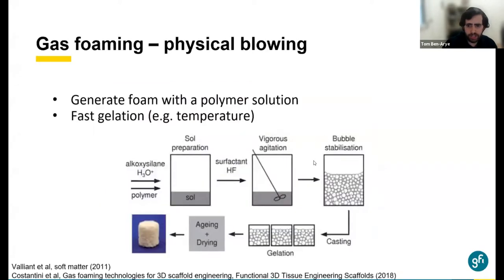Lastly, I will mention this interesting direction of gas foaming. You basically take a solution that contains the polymer that you want to generate the scaffold from and a surfactant. You mix it until you get these bubbles that are stable. And if the gelation happens inside the foam that you have here, we will maintain the structure of this porous structure that we see here, and then we can generate the gels that we are interested in. The advantage is that it's kind of scalable, and it can also fill the container that it's inside. It could be interesting for scalable processes.